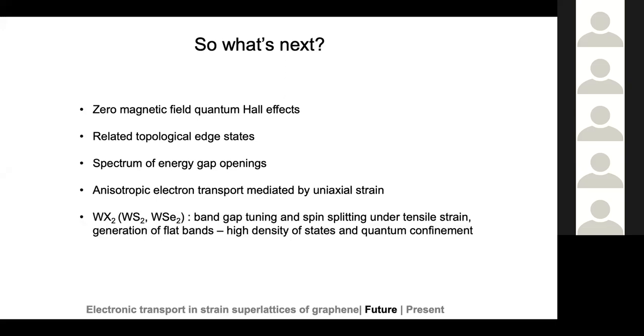And we also plan to move on to other 2D materials and see how the strain superlattices look for them. For example, transition metal dichalcogenides, big name, but essentially materials like tungsten disulfide, tungsten diselenide. What happens under strain is that the band gap can be tuned, and also there are flat bands which are generated. These have a high density of states and have been seen to show quantum confinement.